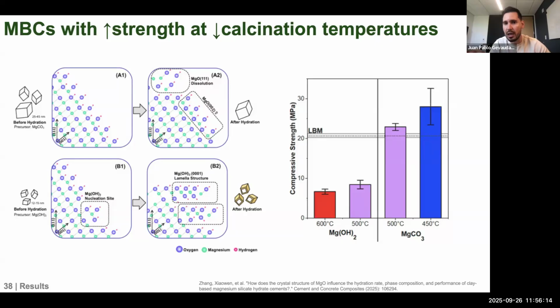So this horizontal dotted line, that is the same. These are all the same magnesium-based cement formulations being formed, casted and tested. This straight dotted line here is one made with lightly burned magnesia. And what you see on the left and the right here is for magnesium carbonate or magnesium hydroxide derived magnesia. And what we see here is that at lower temperatures of 450 or even 500, we have statistically higher mean compressive strengths than if we are producing the same cement with a lightly burned magnesia or even magnesia from brucite.